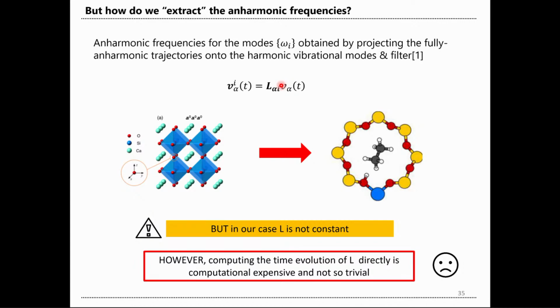But also, in the case you say, okay, I want to pay the price, I want to do it, it's not even so trivial, because the L matrix is well defined only if you are at the minimum or around the minimum position of your potential energy surface. But when you are outside the minimum, and we are doing this molecular dynamics simulation because we want to describe also the points that are far from the minimum of the potential energy surface, in a way to include this anharmonic contribution, the L matrix is not so well defined. It's why the direct calculation with static calculation of the harmonic frequency is so complex and computationally expensive. So we are stuck with this.